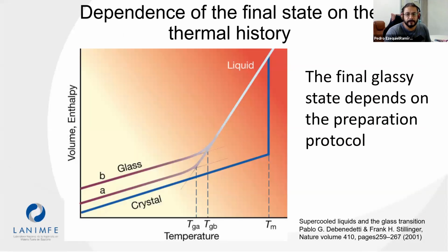One of the most important observations in glass formation is that during measurement of thermodynamic properties near the glass transition temperature, for example, a specific volume or enthalpy, we can find a strong deviation from the equilibrium behavior. I mean, these values deviate from the corresponding values at the crystalline solid or the supercooled liquid, which are the equilibrium states of reference. As illustrated in the figure, where the red line differs from the blue line and the extrapolation of the white line.